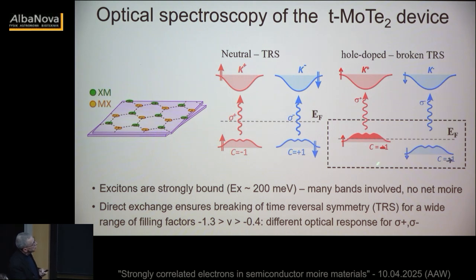So when the Fermi energy is pushed into the valence band, all the holes for a large filling factor regime occupy one valley spontaneously. This is energetically favorable, and the way to understand this, at least I understand it, is direct exchange. Right? So we know that exchange favors polarization. That's Hund's rule, right? And why electrons are spin polarized in, let's say, carbon and nitrogen, etc. But here, this is enhanced compared to other systems because the bands are topological, have a finite Chern number, which means that they cannot be exponentially localized. They really cannot avoid each other if they have a different spin. Therefore, the exchange effect becomes more important.